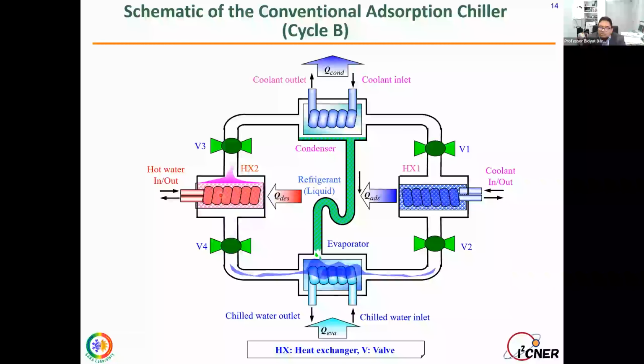What we are doing here is we close all 4 valves, and instead of cooling water, we use some hot water here. So we are preheating this cycle, and at the same time, instead of hot water, we are using cooling water here, and so we are pre-cooling this cycle. This bed will go to desorption mode in the next 7 minutes, and this will work as the adsorption mode in the next period. That's why we call it the preheating and pre-cooling mode for this cycle.